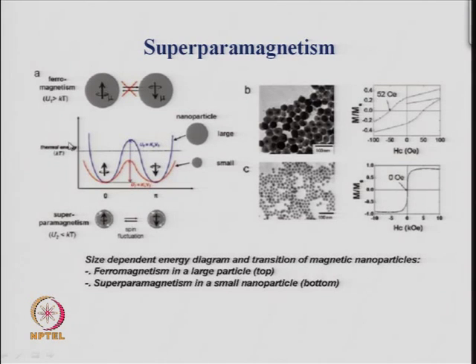If you have an energy plot, here is the thermal energy as a function of, say, the orientation of the spins. Here you can consider this to be a magnetic moment, and if you are in this stability zone, that means the energy is minimum here for one direction and the energy is minimum here for the other direction of the magnetic vector. If you want to go from this direction to this direction, you have to overcome this energy barrier.